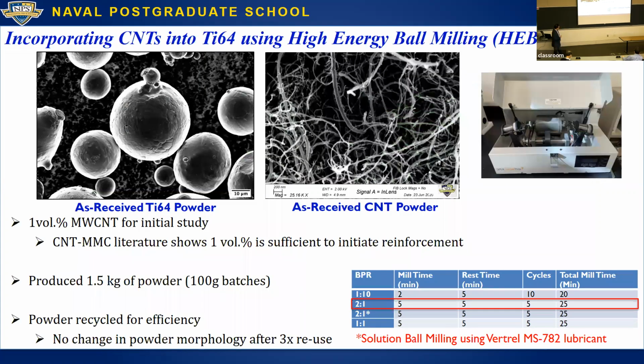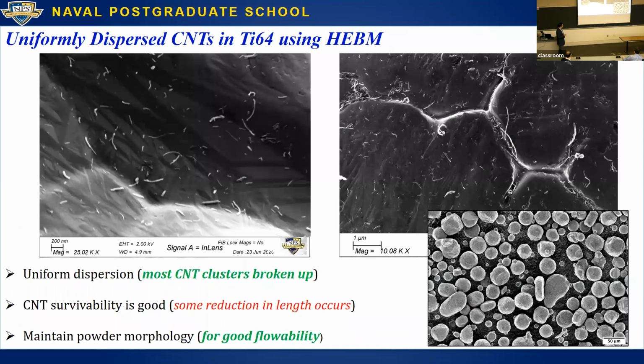So these are some of the specifics as to how we made the powder. This is the kind of CNT that we were using, and we tried different milling techniques. We tried using solution ball milling where you have a lubricant, but we actually came up with a processing routine. This is more on the engineering side of it. We have guiding principles, but we came up with a solution where our powder is quite good and we can actually reuse it several times and still be able to print with it.